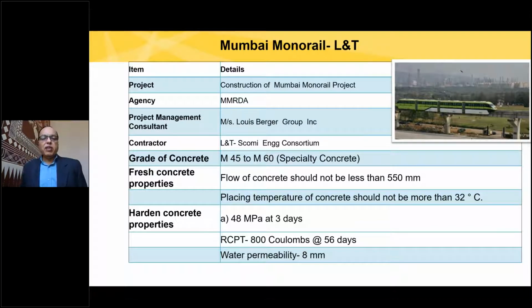Maybe it is M45 or M60, but even M60 should have 48 MPa in 3 days. Within 3 days, it should gain 48 MPa. That means high early strength concrete is required, and the RCPT, rapid chloride permeability test, which is a measure of durability, should yield not more than 800 coulombs at 56 days, not at 28 days, 56 days. Both chloride permeability is measured, water permeability is also, there is a limit.